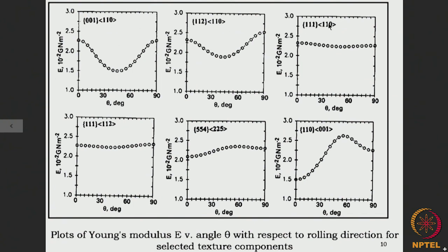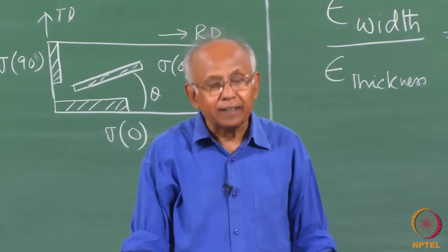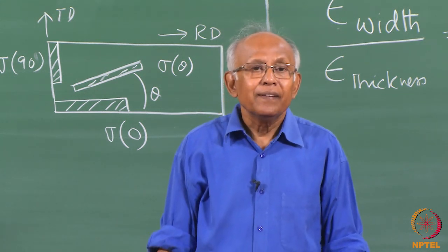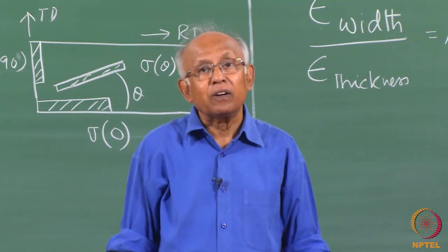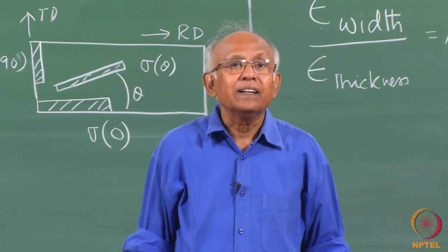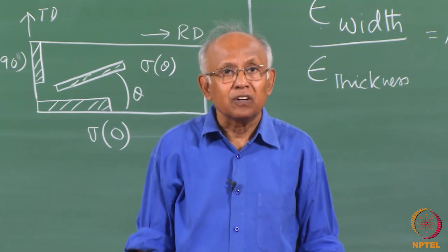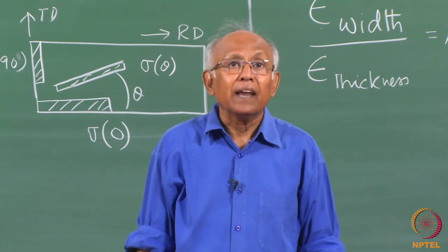You see, Young's modulus is a structure insensitive property. That means by changing the microstructure, you cannot change Young's modulus. But Young's modulus is very much a function of the texture of the material, and that is amply shown by these diagrams. So finally, I would like to say this much, that texture is very much important, just like microstructure. In our undergraduate days, when we were young, we were told that property of a material is a function of its microstructure, but this is no longer so. Now we know that property is a function of microstructure as well as texture, and the importance of texture is growing day by day, and therefore this can no longer be ignored.